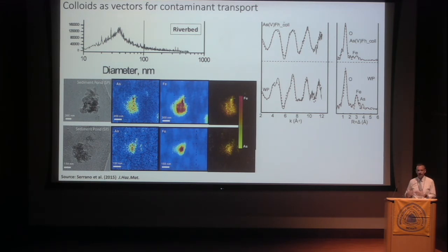This was coming back to arsenic and coming back to iron oxides. This is a study in Spain that used asymmetric flow field flow fractionation with ICP-MS. And so they can take the stream of particles and separate them out by particle size, send that through the ICP, and then determine where, in this case, arsenic or other trace metals are found as a function of size fraction. And they could see that the arsenic was primarily associated with these nanometer scale particles that were described by TEM with EDS and then by XAS as iron oxides, but a mixture of iron oxides and organic matter that are transporting arsenic out of these systems, and often long distances from, and at the kilometer scale, long distances from where they're forming.